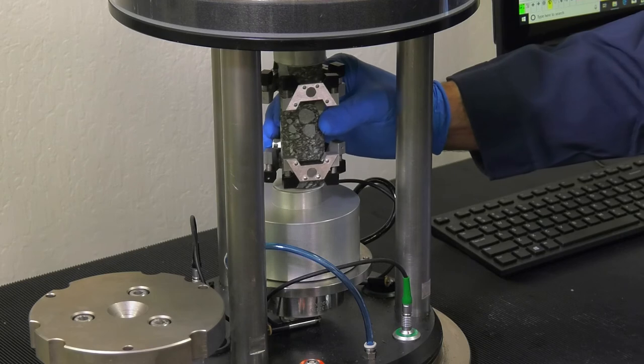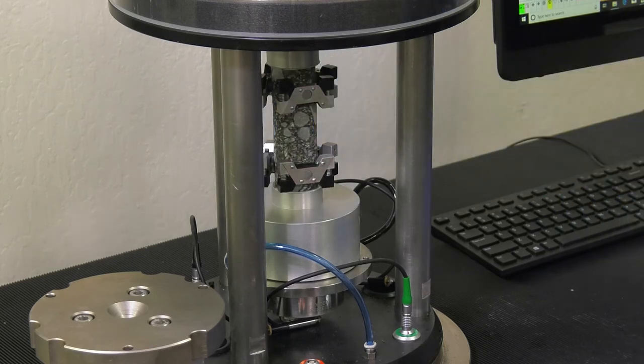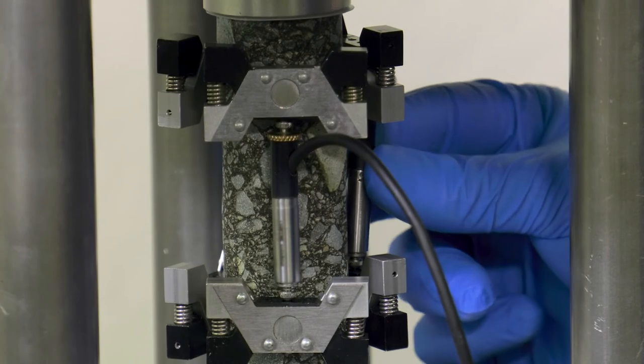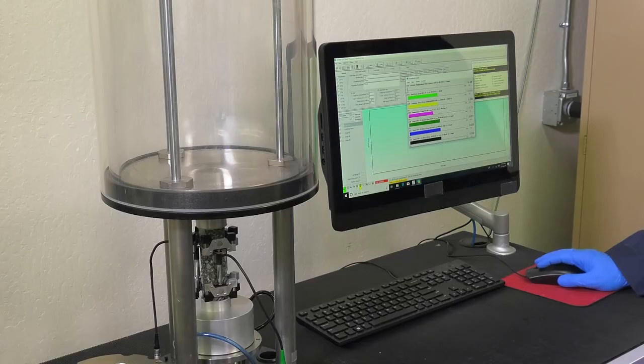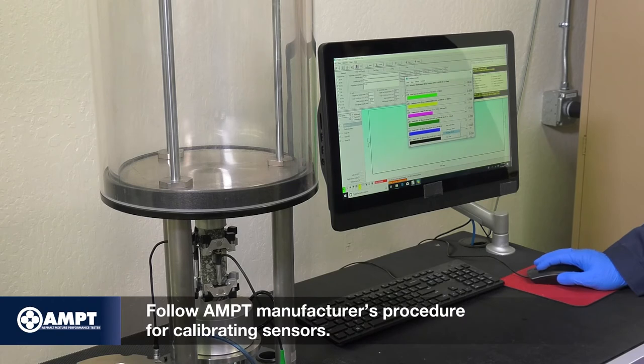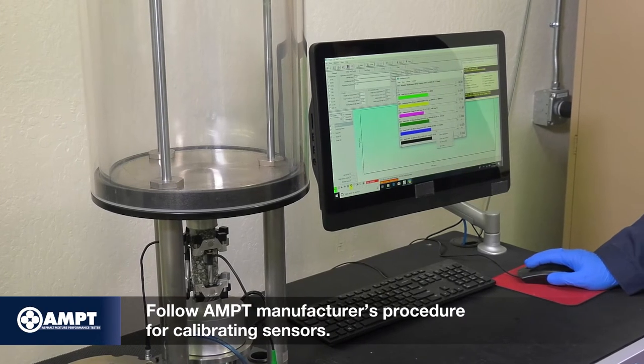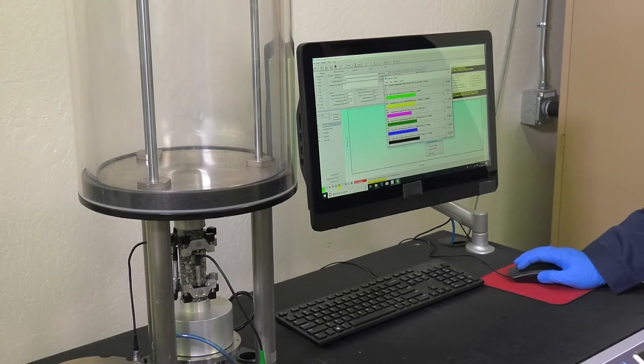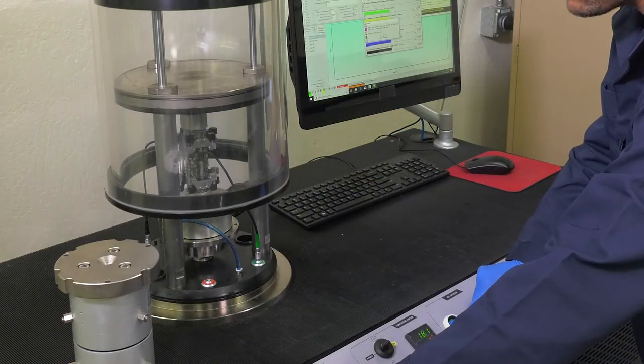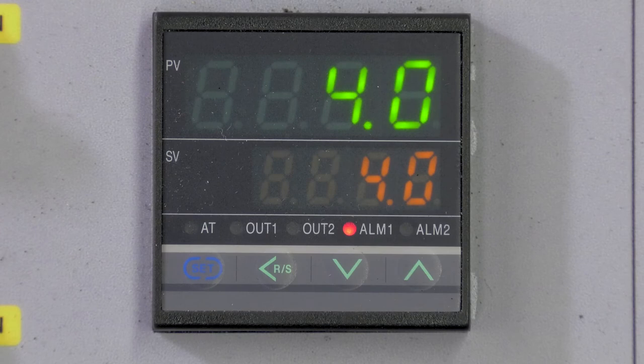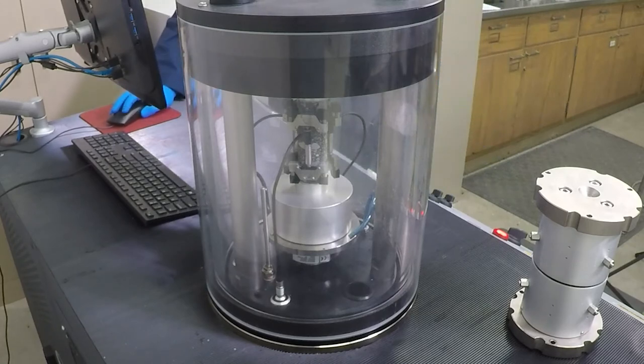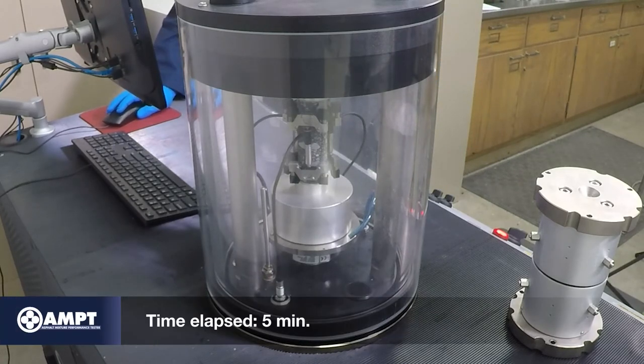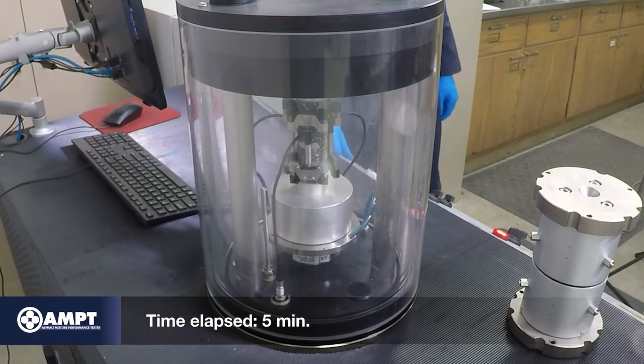Carefully center the specimen on the contact surface of the bottom platen with PTFE sheet and install the LVDTs between the LVDT clamps. Once the LVDTs are installed, ensure the LVDT readings are adjusted to accommodate the deformation range of the test. It is typically set to zero to accommodate displacements due to compression and tension. Close the AMPT conditioning chamber. Allow the chamber and the specimen to return to the test temperature. According to the standard, setting up the test specimen in the AMPT conditioning chamber and returning the chamber to test temperature should not take more than 5 minutes.